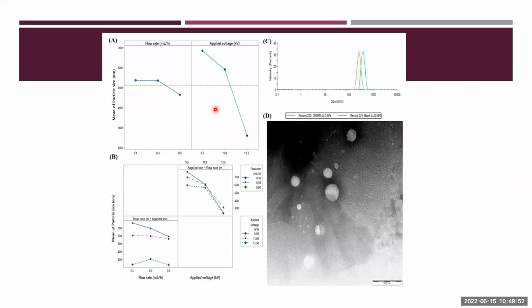So again, you will always find a study of flow rate and high voltage, and commonly high voltage has the most significant effect on the size. When you increase the voltage here, you can see the voltage is higher, between about 9 to 12.5 or 13 kilovolt. So the size drops from 700 nanometer down to about 250 nanometer. And this is under the TEM.